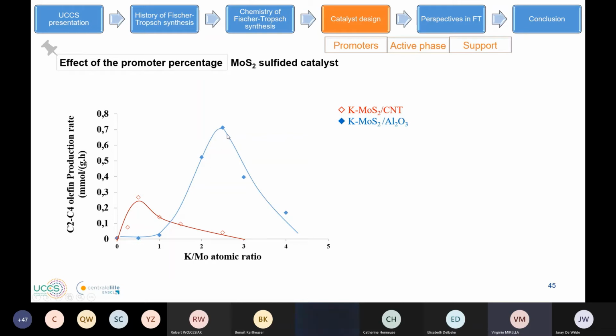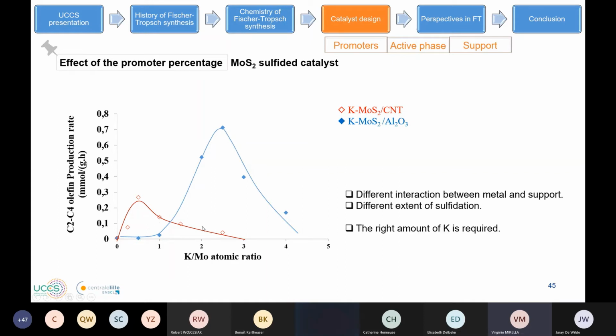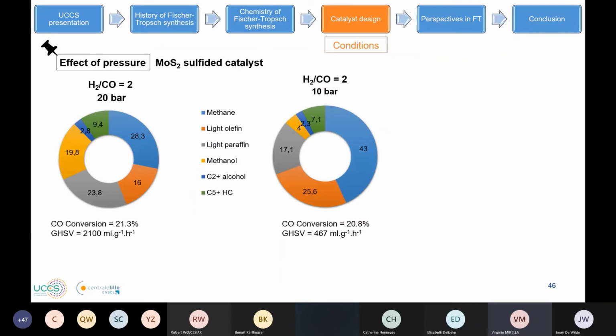So when we use too much potassium, we decrease the selectivity of olefin. And this observation has been made for alumina support and also on carbon nanotube support, meaning that we need to have large particle size. We need to add potassium to increase the selectivity in olefin, and we have to put the right amount of potassium to improve the selectivity in olefin.